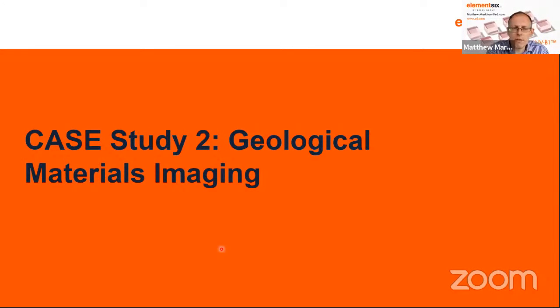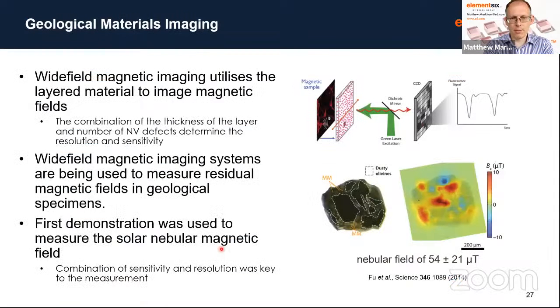So moving on to a very different type of application area. This is something that's been going on in the geological community for a few years now, and I think is building up due to some of the work that Roger Fu at Harvard has been doing. This is using diamond in a different imaging modality. The previous one was all about using ensemble defects, and I talked earlier about generating these layers of NV defects in diamond. The advantage of that is you can then use a CCD system to map the position on the diamond against the position of your sample. So you're able to spatially map out the magnetic field of a particular sample that you might be interested in.